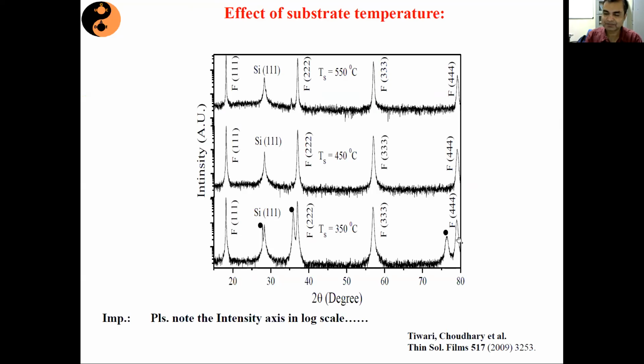So that means these films had some impurity phase or secondary phase different from Fe3O4, different from the required one. The moment the substrate temperature was increased to 450 degrees centigrade, we got an entirely oriented, textured film. So that is something we have to really understand: the substrate temperature plays a very crucial role in determining the phase of the grown film.